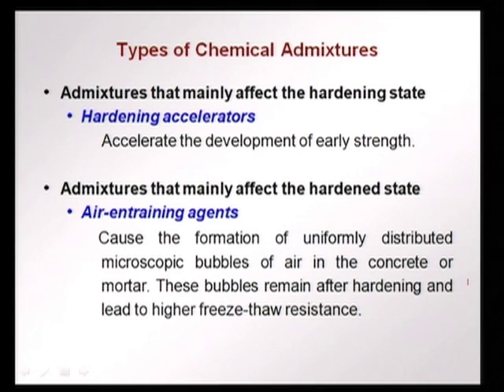When we have freezing and thawing cycles in concrete, the water that is in the capillary pores expands as it freezes, or even before freezing it will tend to expand and move in the capillary pores, and if there is not enough space for free expansion, this expansion could lead to cracking of the concrete because of the expansive forces of the water becoming ice. Therefore, to compensate this, air entraining agents are used to create a set of uniformly distributed microscopic bubbles of air in the concrete or mortar. This provides space where the water can expand and become ice, and these bubbles remain even after hardening, and consequently we get higher freeze thaw resistance.